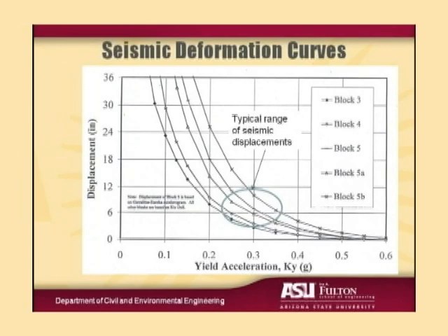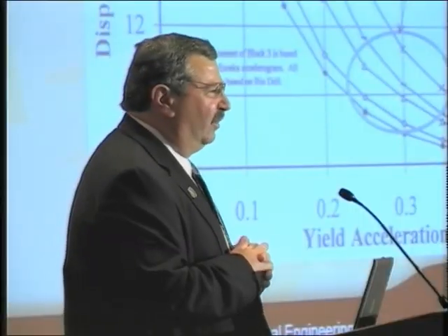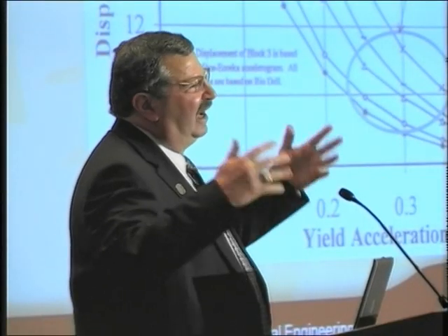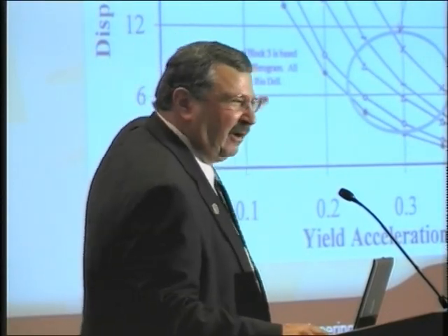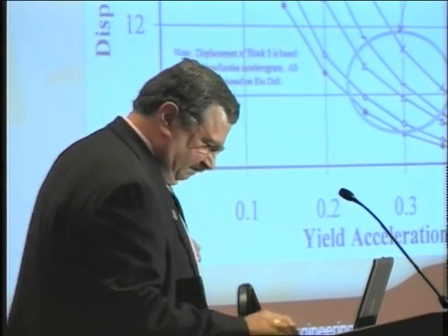12 inches of seismic displacement in this large solid waste mass, 12 inches of calculated seismic displacement, I should mention that the type of analysis we're doing is generally conservative and generally overestimates the actual seismic displacement, was considered acceptable seismic performance for this and the maximum credible earthquake. We used to say, well, all the bridges will fall down and none of the hospitals will be operating, but our landfill will still be standing.